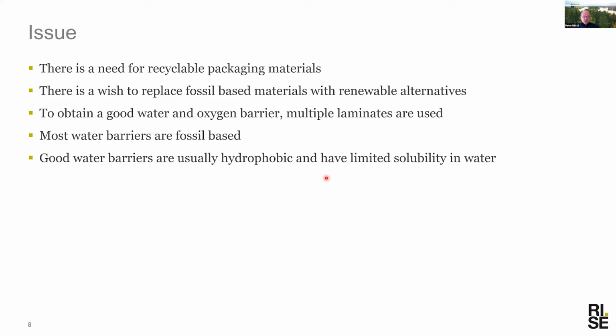The second one, when we look at replacing fossil-based materials with renewable alternatives: for oxygen and grease barriers, we have alternatives. We don't have that many alternatives when it comes to moisture barriers. Also, when we look at a good water and oxygen barrier, we use multiple laminates to get the best of each material, but that tends to be a little bit harder to recycle. What I have seen is that we have quite a lot of water barriers that are fossil-based. There are, of course, exceptions. In that case, you can use wax-based barriers, and so on, as water barriers.